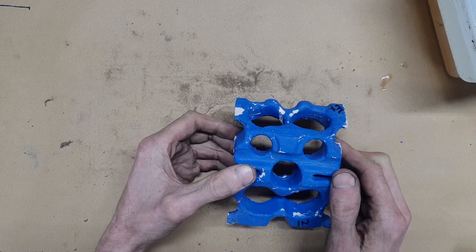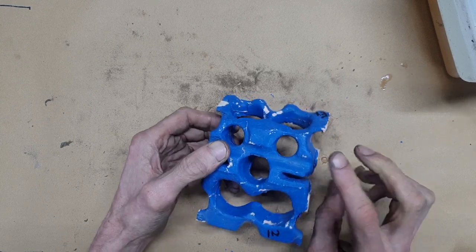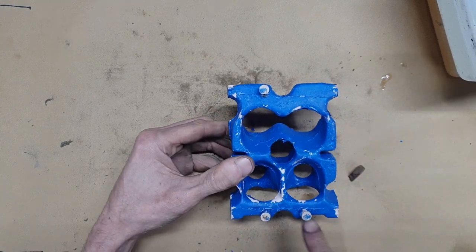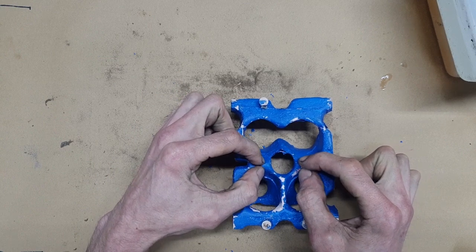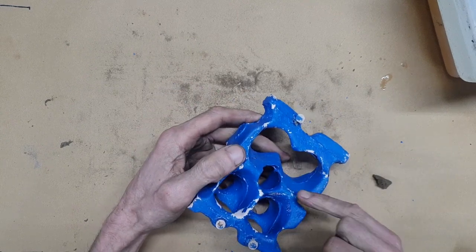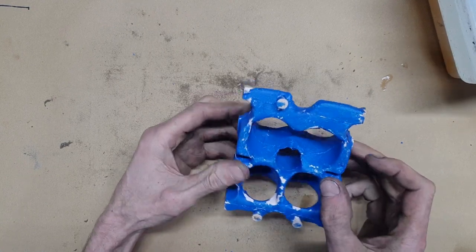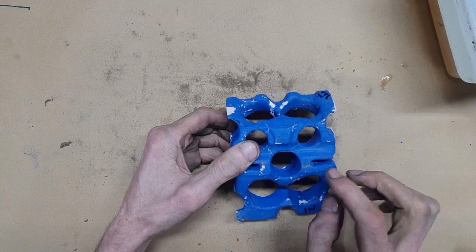So in 2009, a company called, I can never think of the name of it, Southwest Research Institute, came up with an idea where you could use a large sand mold, normal for the big parts, and put in a very small, really tiny part in the middle. You could bond a small ceramic high definition part into the middle of it, which resulted in them being able to form very thin coolant ways here, here, here, here, and also meant you hadn't got a huge mass of aluminium, which, as you know, when you pour aluminium,